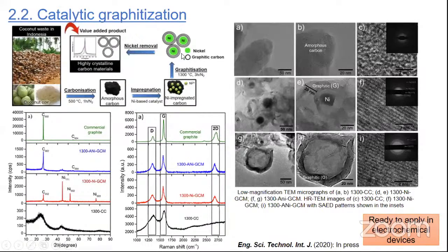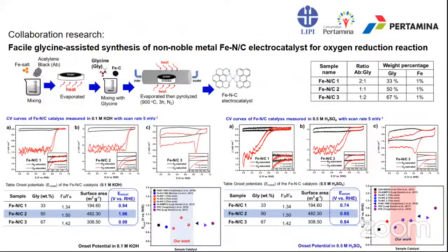We use a nickel catalyst to reduce the temperature of graphitization. And we can see from the TEM that we have very good crystallinity, I think. And our sample is ready to apply in electrochemical devices, including anode in lithium battery, GDL in fuel cell, and also supercapacitor. And also we have collaboration research with Universitas Pertamina and Pertamina Company to make a Fe-N-C electrocatalyst for ORR reaction.